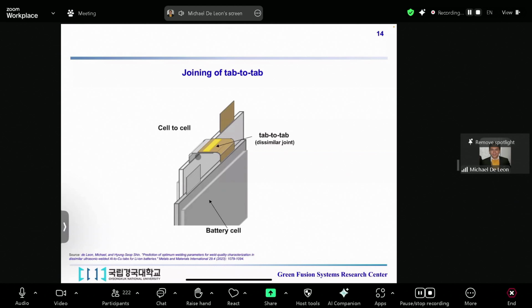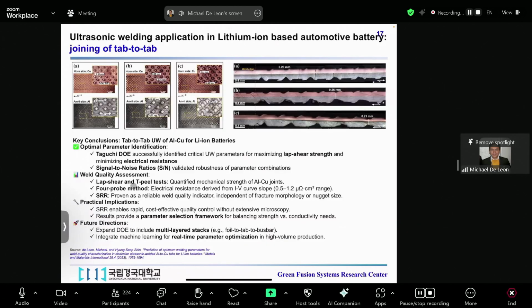And for the key findings of tab-to-tab ultrasonic welding, through the Taguchi design of experiments, we successfully identified the optimal ultrasonic welding parameters that maximize the mechanical strength while minimizing the joint electrical resistance. Weld quality, on the other hand, was systematically assessed through mechanical testing and electrical analysis, with the strength reduction ratio proving invaluable for rapid quality control, which enables defect detection without doing microscopy by comparing only the SRR results to the lap shear results. And looking ahead, we aim to expand this methodology to multi-layered battery stacks and integrate machine learning for real-time parameter optimization.